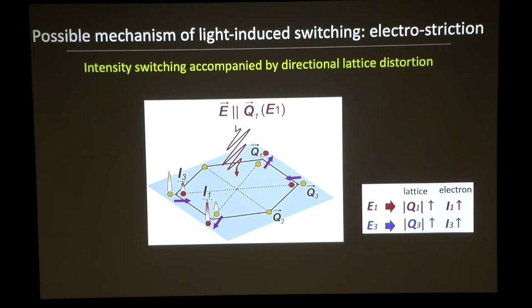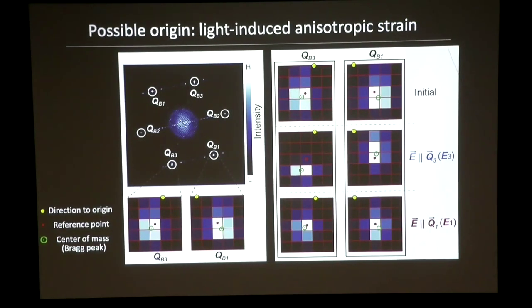The interesting thing about STM is we can check this. So we can actually ask the question, if in a given direction the charge density wave gets stronger, right? If light makes this CDW higher, then do you have more lattice distortion in that direction? So the way we do it is we look at these Bragg peaks. There are six of them. They represent the lattice positions in the three directions. You can zoom in on these Bragg peaks. So I've zoomed in here on this Q3, right, this one. And I can look at what happens to the position of this Bragg peak when you shine light. And you can see that when I shine light along Q3, this direction, the position of this shifts. So it shifts from here to here. And then when you shine light along Q1, this shifts back. So the Bragg peaks move when the charge density wave gets stronger.